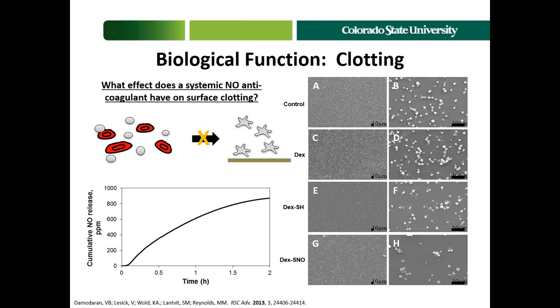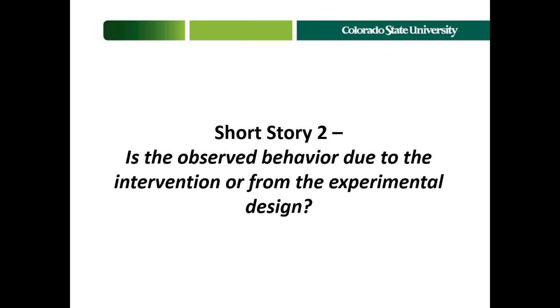So what we actually find in this case, looking at G and H, which is our active surfaces, is that we get significantly less platelets onto surfaces that release nitric oxide, and at the same time we see functional platelets that are actually there available for clotting when needed. So we've been able to look at both cellular behavior of the platelets or cells of interest as well as their dose response profile, and also checking to make sure that the cells are functional.